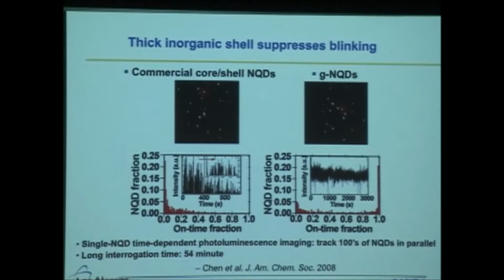And this is all very much a function of the shell thickness. We seem to have some thresholding. These are the first results. In this case, about 20-some% of the ensemble of quantum dots were exhibiting completely non-blinking behavior. Since then, we've increased that percentage dramatically, and I'll show you that result in a second.